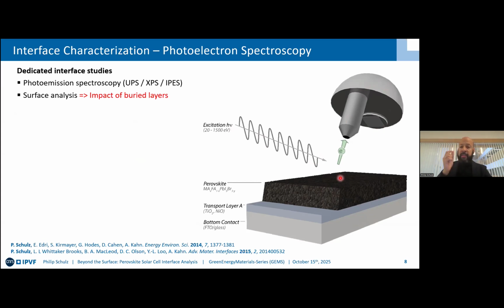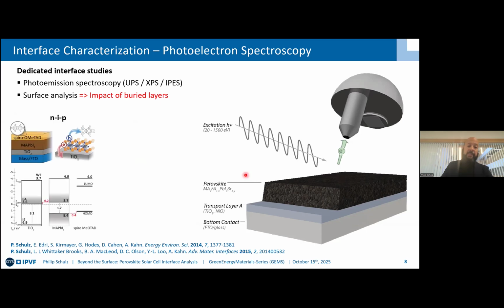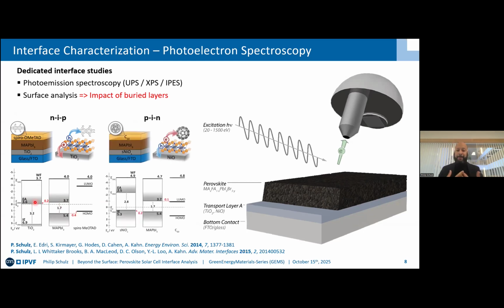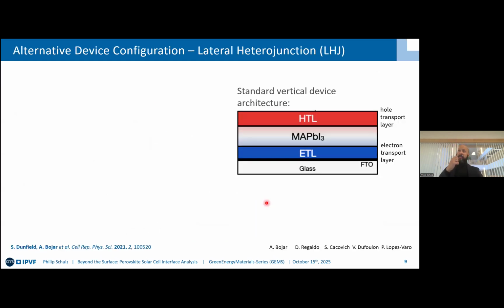Nonetheless, we know that this surface analysis is still very strongly affected by the impact of the buried layers underneath. So for instance, if you start to construct your energy diagrams from this measurement and you measure just MHPs, so MAPI in short, on top of titanium oxide, you will find that at the top of the perovskite layer, the Fermi level is closely aligned to the conduction band, as the perovskite has been deposited on an N-type layer. If you deposit the perovskite on a P-type layer, for instance here, sol-gel nickel oxide, you find the Fermi level to be somewhere in a mid-gap position. So even though we are just sensitive to the first 2 to 5 nanometers, the impact of the layer underneath, buried 400, 500 nanometers below, still plays a significant role on the energy level alignment, as it seems. It is now very hard to assess this interface, but this is what the talk is about eventually.